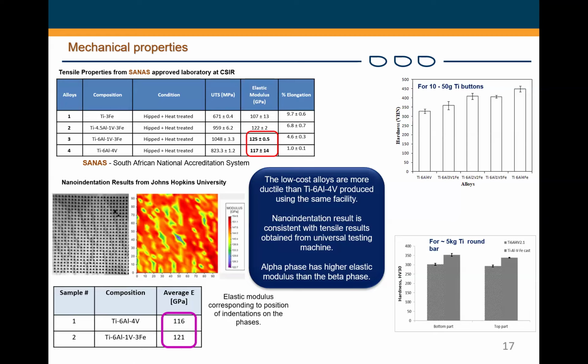And one thing that I want to also show here is that consistently you will see that when you have partial substitution of vanadium with iron, we have higher strength and higher ductility compared to when you have the standard alloy, which is Ti64. And we produced these alloys under similar conditions. So, which means that iron does not only improve strength, it also gives room for ductility. And of course, the reason for that is you have increased beta phase, the BCC phase, as you add iron, because iron is a beta stabilizer anyway. So, that takes care of the mechanical properties.